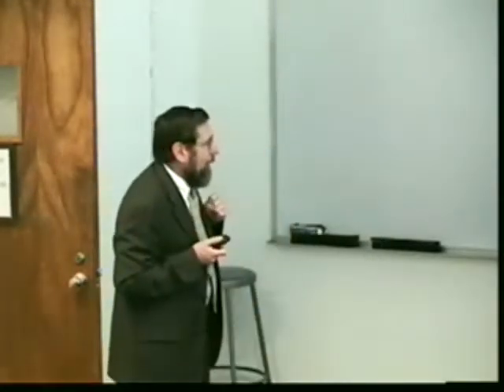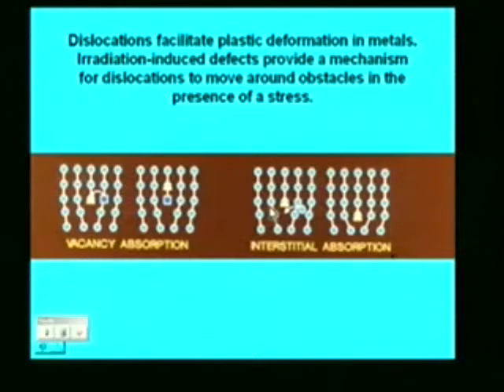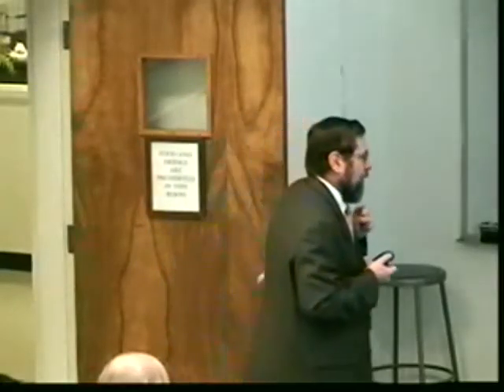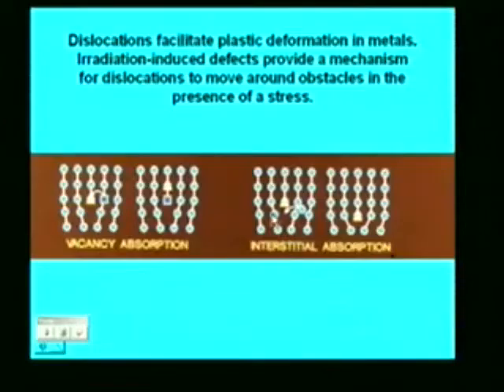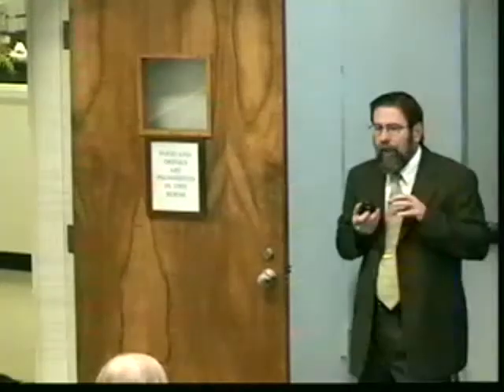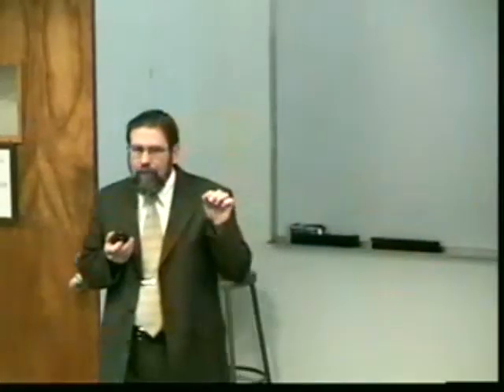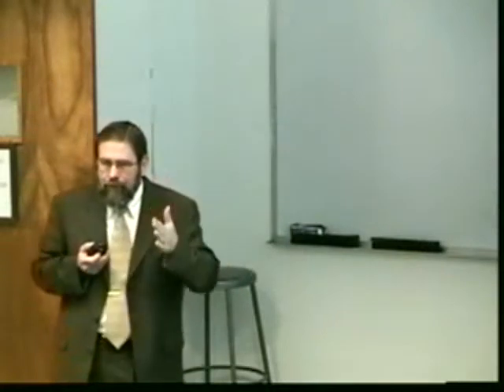All right. Well, we have lots of vacancies and interstitials around. Vacancies cause it to move up, and interstitials cause it to move down. So we have both. On the average, we don't go anywhere. But if we introduce a stress, then we can change things. Because if we had a tensile stress there to pull atoms apart in that region, it would be more energetically favorable to have an interstitial there. So now we can have interstitials predominate over vacancies, and now that dislocation can move. And this is one of the mechanisms of radiation creep.